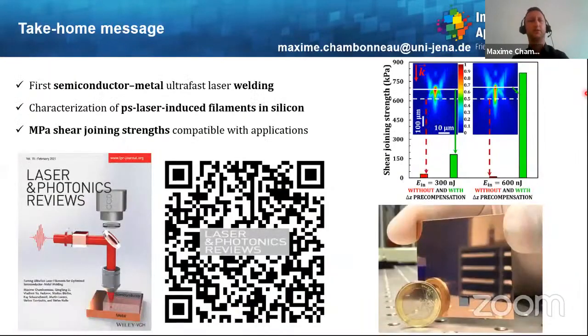So here is the take-home message for this part. So first, we have achieved the very first semiconductor to metal ultrafast laser welding by characterizing picosecond laser induced filaments inside silicon. We have measured megapascal shear joining strength that is compatible with applications. And if you are interested in this topic, please feel free to scan this QR code here, which will lead you to our latest paper on this topic published in Laser and Photonics Reviews.